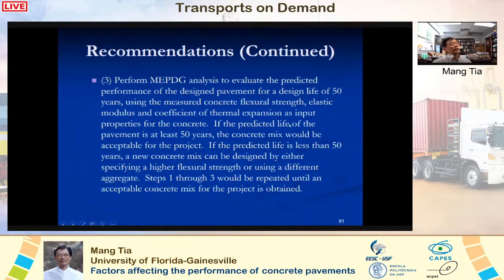If the predicted life of the pavement is at least 50 years, the concrete mix would be acceptable for the project. If it's not, if the predicted life is less than 50 years, a new concrete mix can be designed by either specifying a higher flexural strength or using a different aggregate. And if possible, try to use an aggregate that would give us a lower coefficient of thermal expansion. And steps 1 through 3 would be repeated until an acceptable concrete mix for the project is obtained.